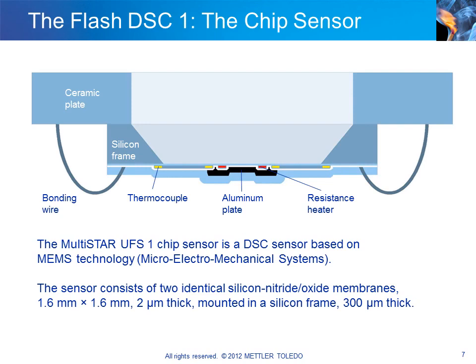Here we see a schematic diagram of the new chip sensor. This is the heart of the Flash DSC-1. The Flash DSC-1 uses the multi-star UFS-1 sensor. UFS stands for ultra-fast sensor. This sensor is a chip sensor based on MEMS technology. The heaters and temperature sensors are incorporated on a small, extremely thin membrane that is only 2 micrometers thick. The construction is in fact a complete miniaturized DSC furnace for sample and reference.